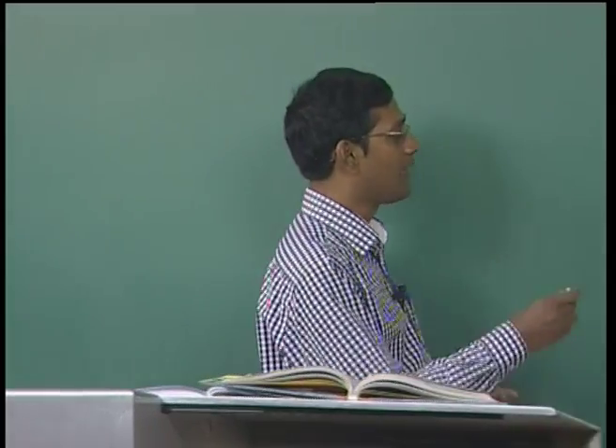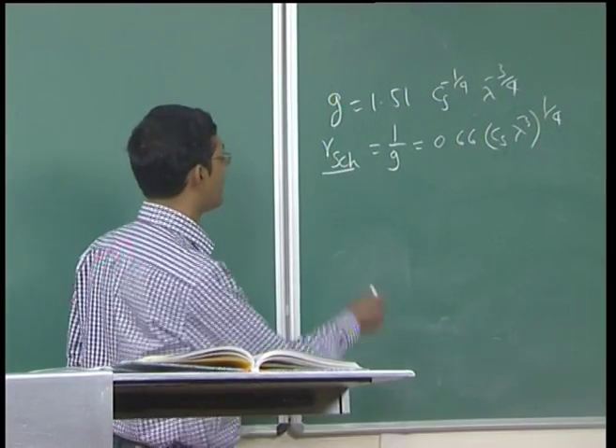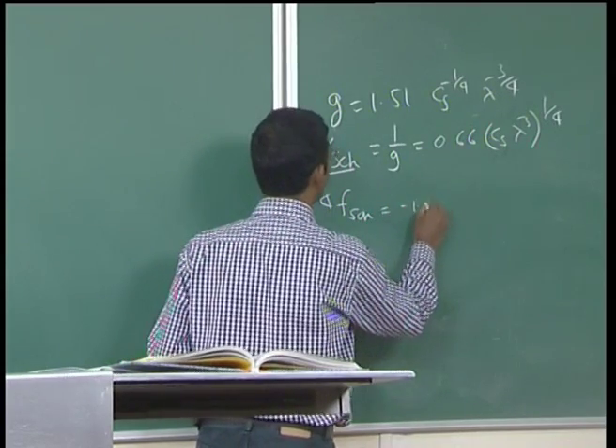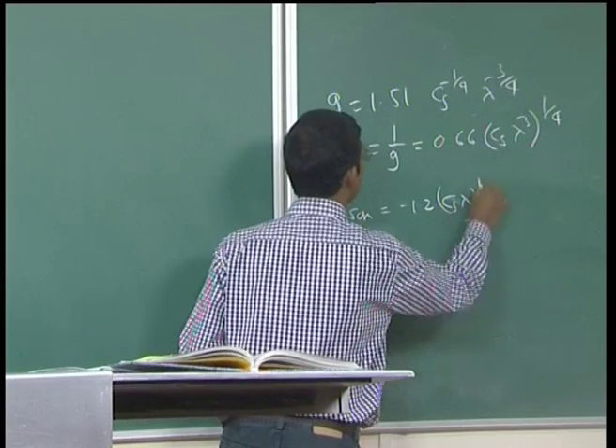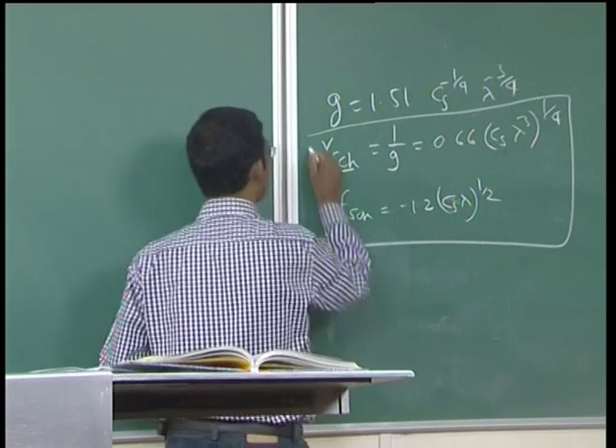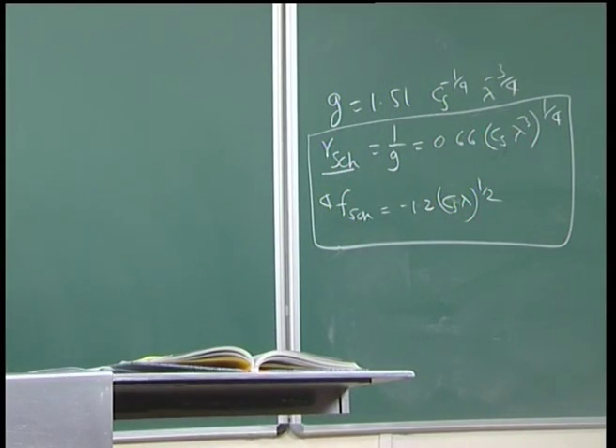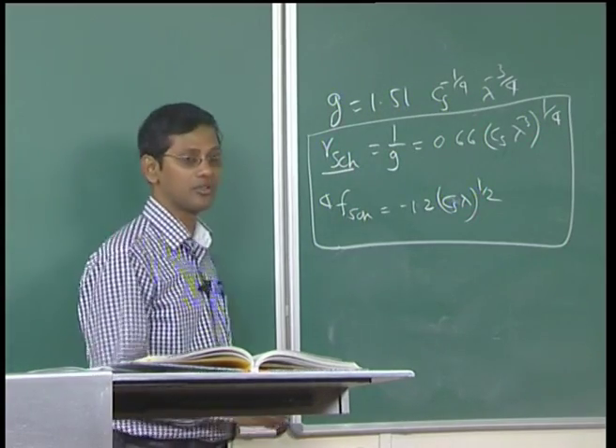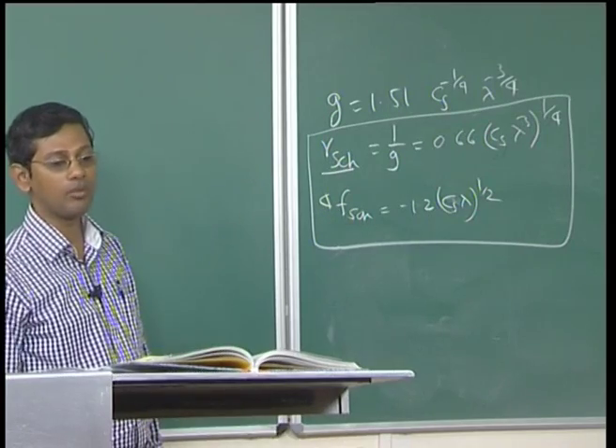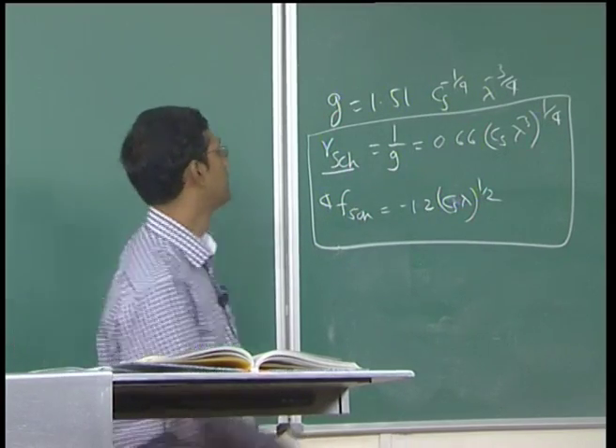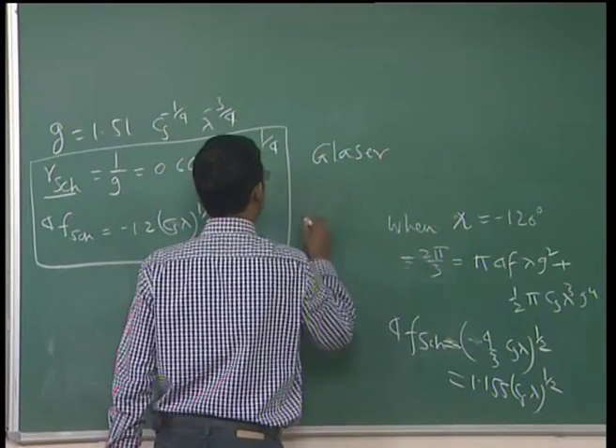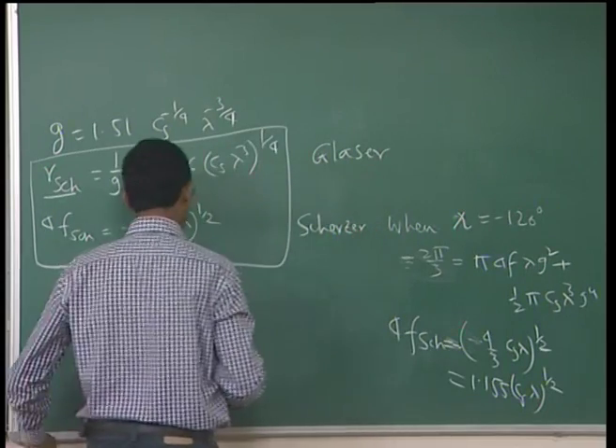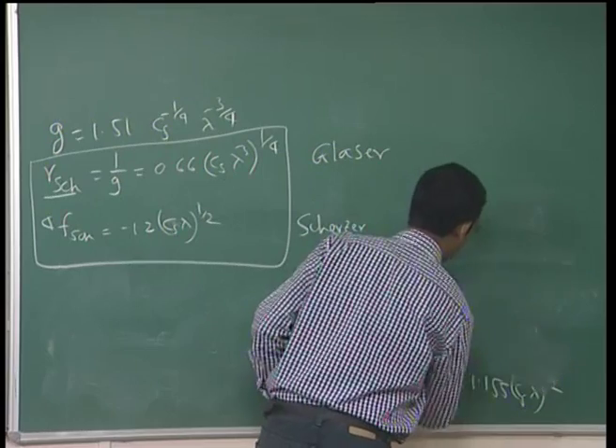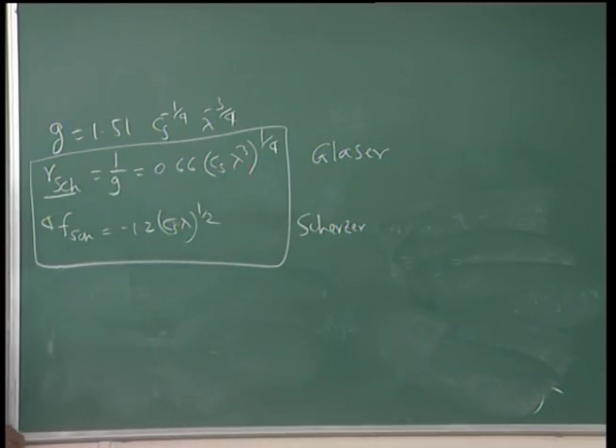Well, therefore, these two functions, one is Scherzer, another one is delta f Scherzer, which is equal to 1.2 Cs lambda to the power half. These two are the master equations in high resolution electron microscopy. They actually give us the limits for any use of the high resolution electron microscope. This was due to Otto Scherzer, and the first equation was basically developed by Glaser. These two scientists are called the pioneers of high resolution electron microscopy for developing this concept. So, that actually sets the tone of high resolution electron microscopes.